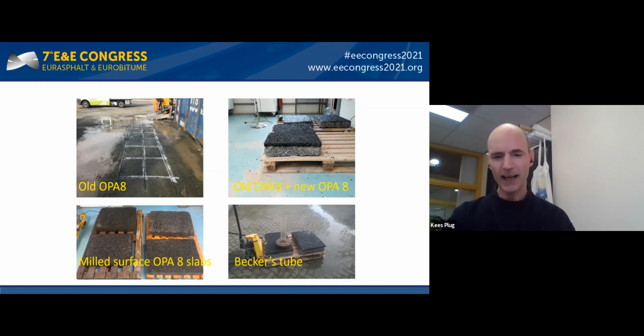First, slabs of old OPA 8 surface were sawn from a road section. The section was an old trial section of the OPA 8 itself. The slabs were taken to the laboratory and different amounts of bond coat were applied on top. The new OPA 8 layer was applied on top with a segmented roller compactor in the lab, which is the finished slabs. The porosity was tested with the Becker tube measurements.